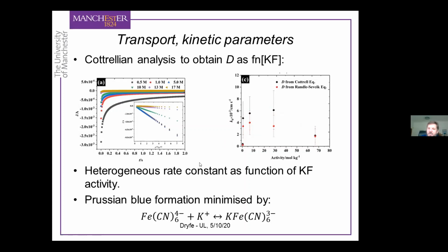And this has been reported before. There was some work, again coincidentally, from Heinz Gerischer with Laurie Peter, when Laurie Peter was a postdoc in the 1970s. And they looked at this phenomenon, at least at the lower electrolyte concentrations, and they saw something similar. And they rationalized it, which our data is consistent with, as an ion pairing. The electron transfer is actually dependent on an ion pairing between the ferrocyanide and the potassium, and that's why you get this apparent electrolyte concentration dependence of the electron transfer kinetics.